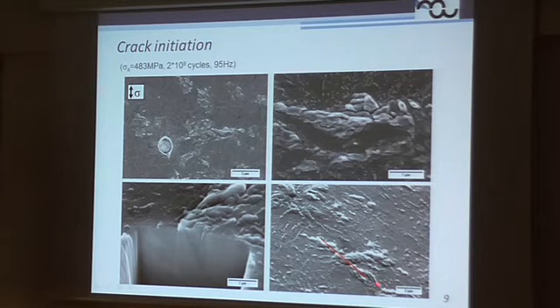To clarify what is going on beneath the surface, we conducted some FIB cutting in this section here, and we relate this shadow here to an ongoing fatigue crack initiation stage. You can also see here a small void.